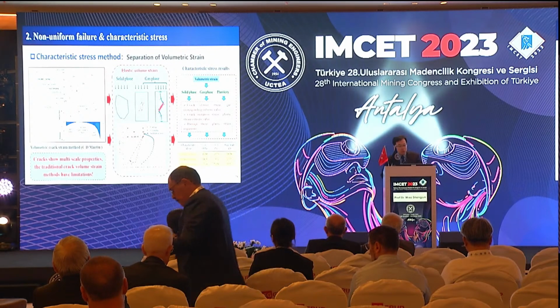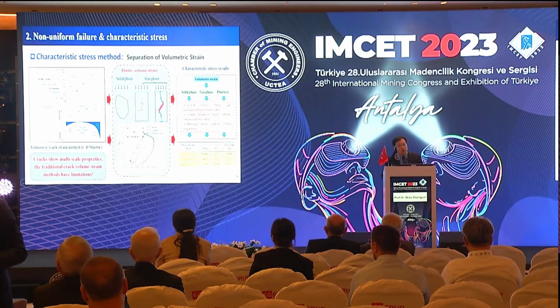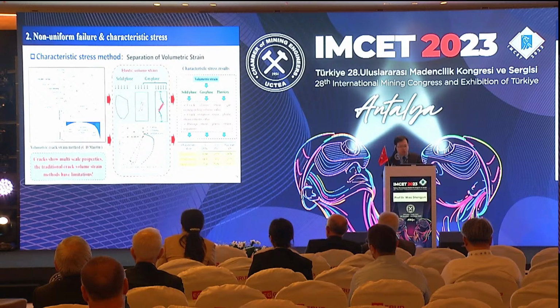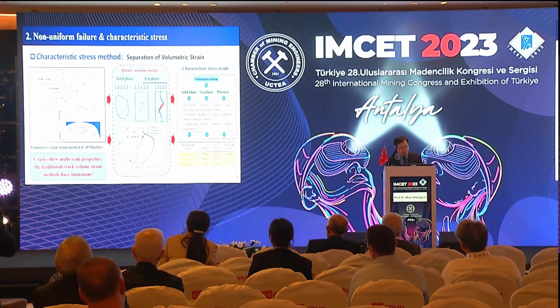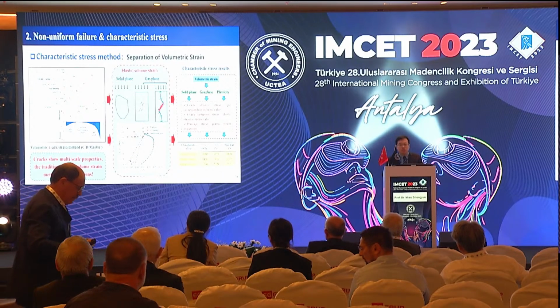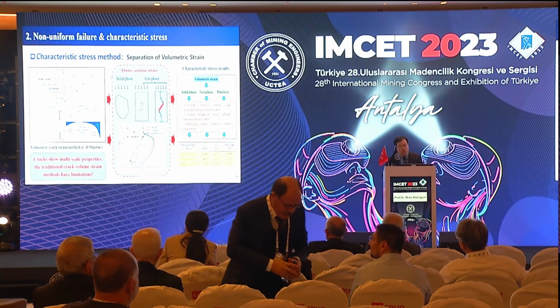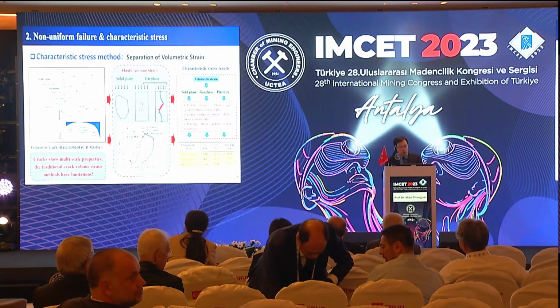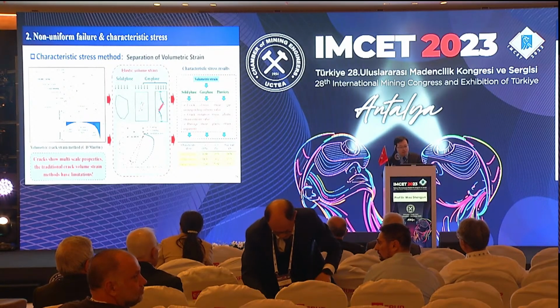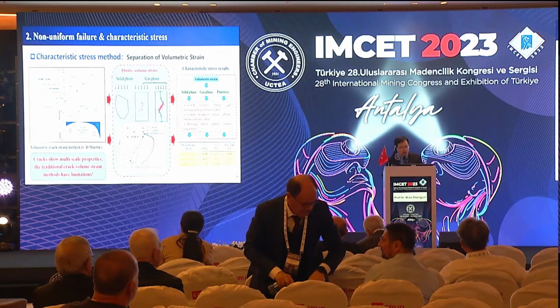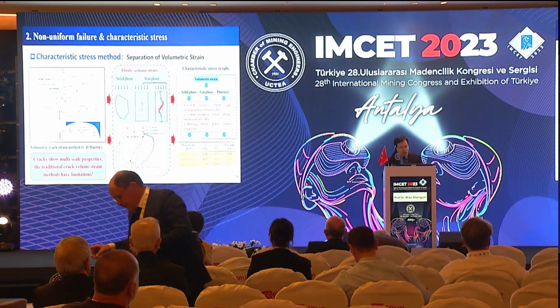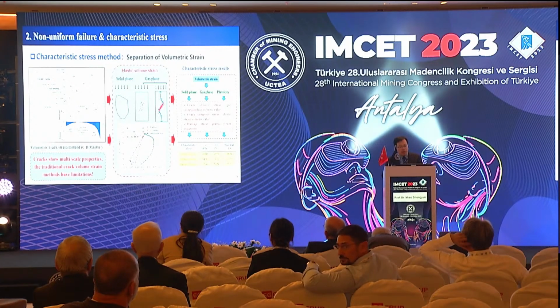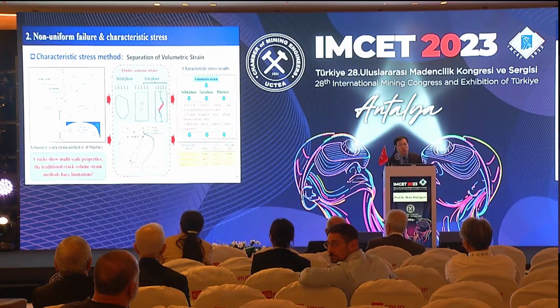Based on the previous research results, we know that the cracks of siltstone show significant multi-scale and non-uniform characteristics. The traditional characteristic stress determination methods have a certain limitation for siltstone. Therefore, based on the CT Martin's method, we further differentiated the volumetric strain of rock into elastic solid phase strain, elastic pore strain, and plastic strain through the step cycle loading and unloading test, and established a new method.